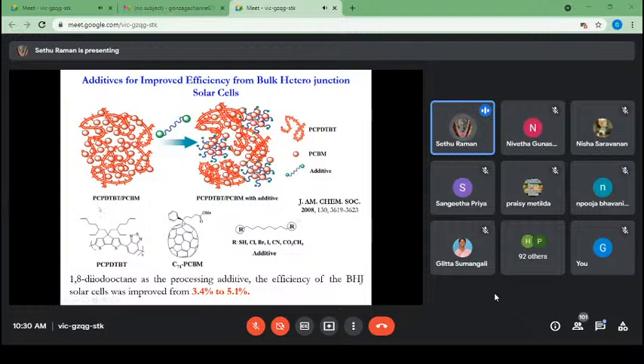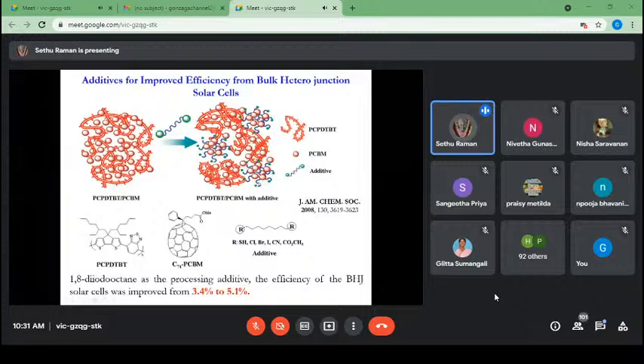They synthesized PCPDTBT and PCBM. BT is a kind of polymer, long chain polymers they prepared, and they used 1,8-diiodooctane as a processing additive. By using this processing additive, the efficiency of the bulk heterojunction solar cell was improved from 3.4 to 5.1 percent. The additive is simply used to segregate the molecules, so that they achieve very good exciton dissociation at the interface,